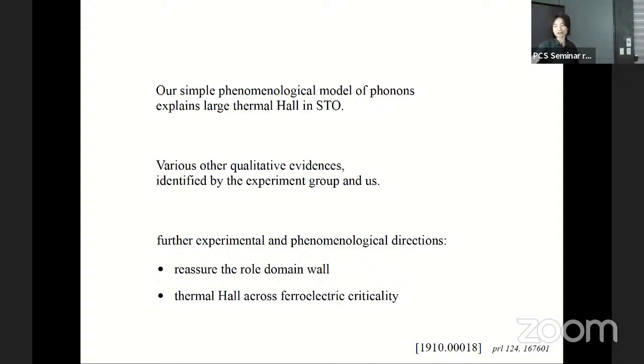And also another thing we can check is if we somehow tune the material so that it goes further towards the ferroelectric criticality, what happens? Those are the predictions. But isn't that right that if you change temperatures, then at large temperatures the domain size is very small, and then they become bigger and bigger? They are frozen. These are not very easily moved domains, it turns out. In the later part, in another material, we'll propose some domains which are easily moved.